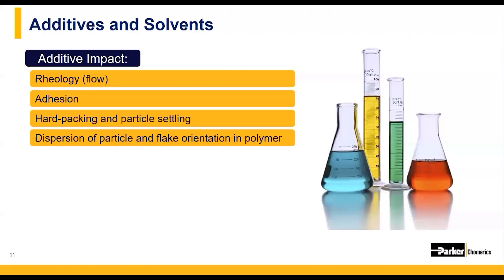Additives are put into a coating solution to impact the rheology, or the flow, of the materials. They work with the various particle fillers to hold metallic particles in suspension for greater periods of time and prevent particle settling. Hard packing occurs when particles sink and create a dense layer that separates from the binder system, making application very difficult. In general, additives are added in very small amounts, usually far less than five percent of the coating solution by weight.